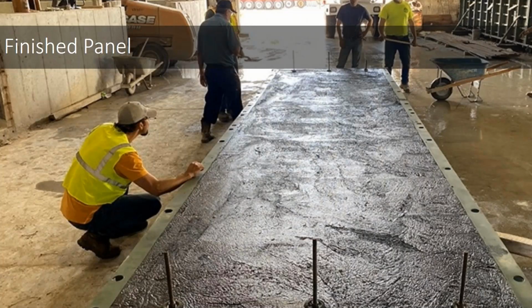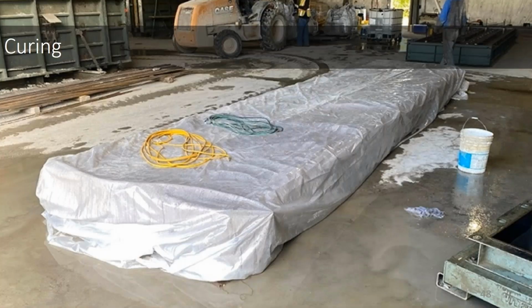So here it is with the fully cast finished panel. It only takes about, I think, 25, 30 minutes. The mix was in there. It's self-consolidating, so you're not vibrating it, because if you vibrate this material, you change the striations, the orientation of the steel fiber. So basically it'll smooth, it'll flow. The top surface has got a little skin to it. It's not perfect, but we've learned to work with that in the end.